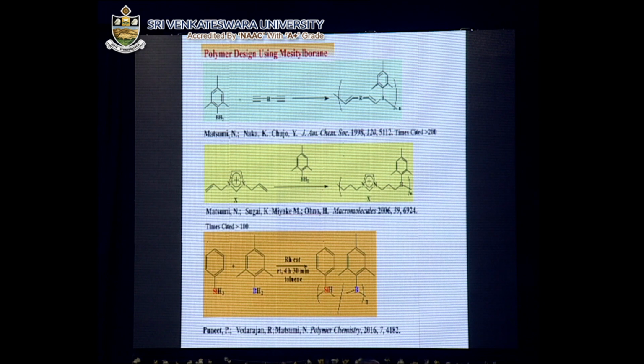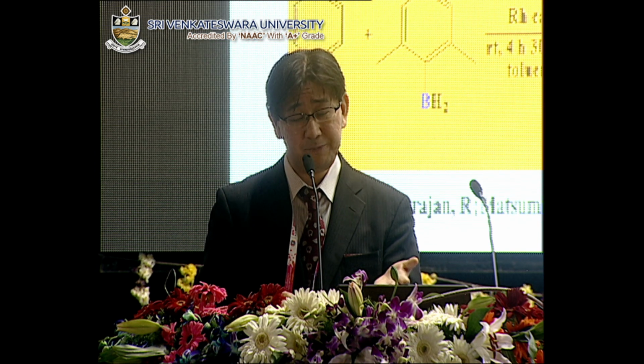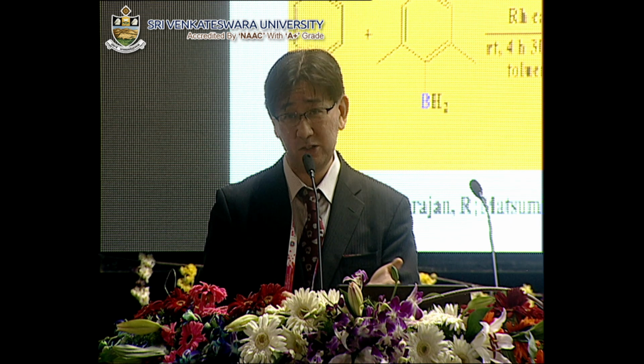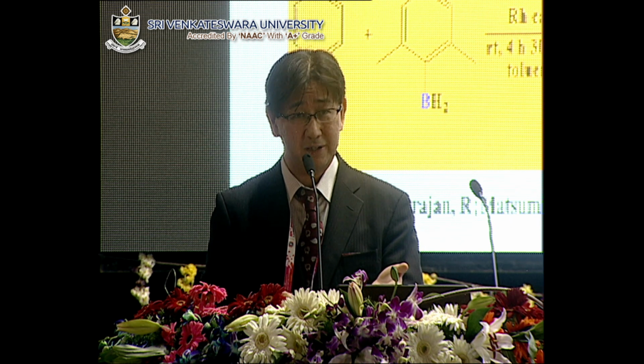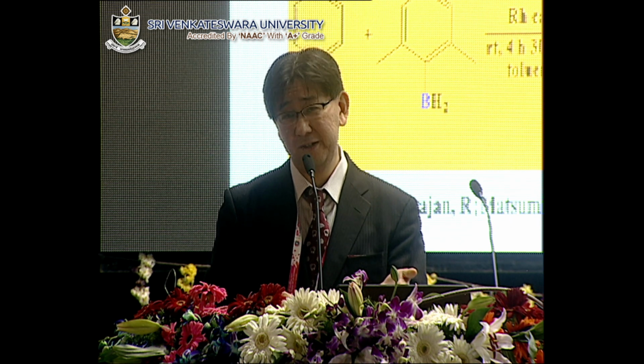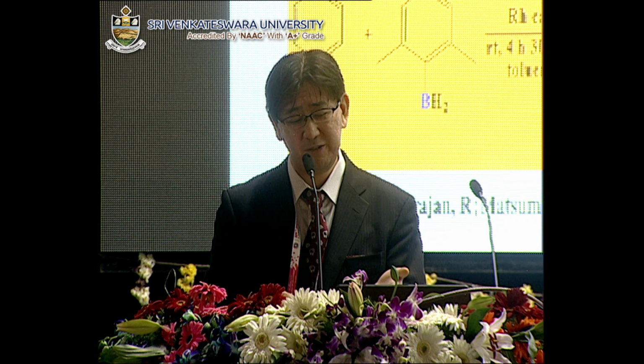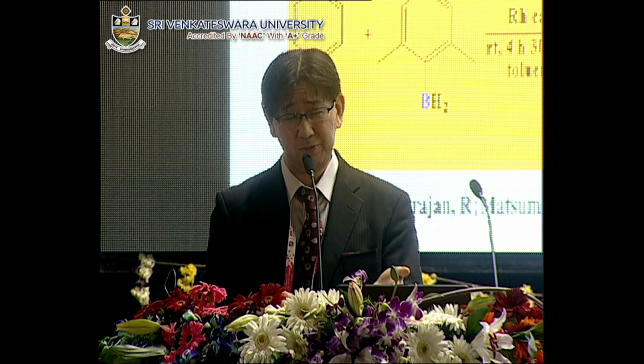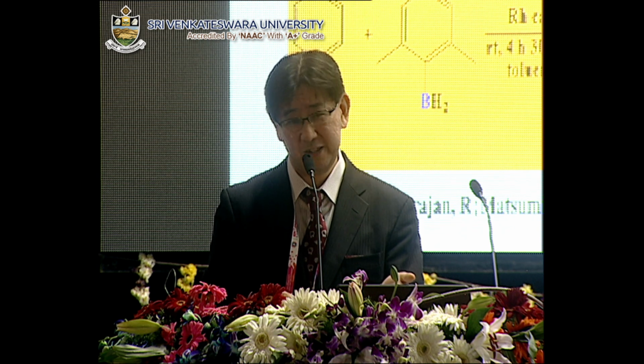Okay, and the final topic is silicon-boron dual inorganic element type copolymers for fluoride anion sensing applications. So far, by utilizing hydroborane precursors, we have developed various types of conjugated materials. For instance, we developed a pi-conjugated organoboron polymer in which the pi conjugation length is extended through the vacant p orbital of the boron atom. This material showed intense blue light emission and a very high third-order nonlinear optical susceptibility, and became commercially available from the Sigma-Aldrich Corporation of the United States.